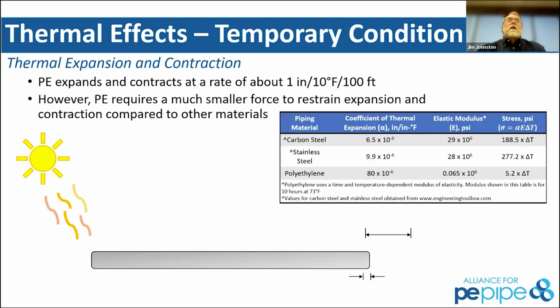Thermal effects themselves, we actually see that polyethylene has a very strong thermal expansion rate. The rule of thumb is a very easy piece to use here, which is 1/10/100, meaning that it will contract or expand at a rate of 1 inch per 10 degrees Fahrenheit per 100 feet of section. Now that's unconstrained. It means if it's just laying on the ground, it will expand or contract at that 1/10/100 rate, but it takes a very much smaller force to restrain that, because the force of that expansion is much less than carbon steel or stainless.